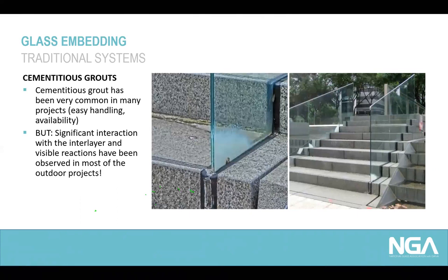So what happens here, we have a cementitious grout. The cementitious material is not compatible with the laminated glass interlayer, and the cementitious filling is also porous and it's absorbing water at outdoor conditions. It's absorbing liquid water quite quick and it's releasing the water very slow. So that means that the laminated glass edge is exposed to permanent wet conditions, causing that strong discoloration of the interlayer here.